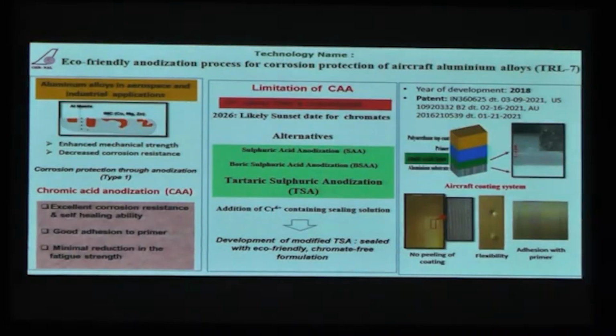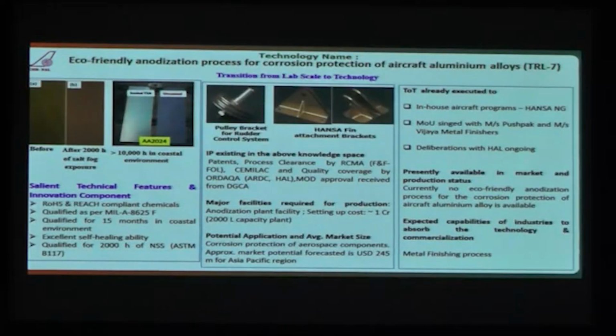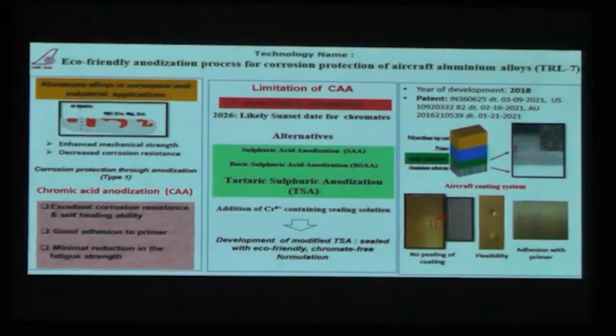So, first and foremost, it was tested for corrosion in a conventional salt spray test, and we have evaluated it per ASTM B117. We have shown that it qualifies for more than 2,000 hours, at par with the conventional chromic acid anodization. Apart from that, we have tested its compatibility with the primer through an adhesion test.